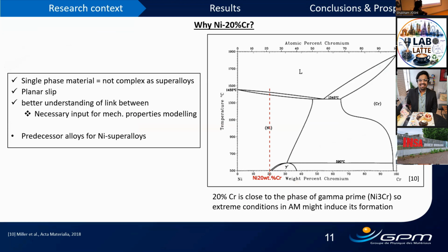If you look at the phase diagram, with 20% weight chromium, it is theoretically a monophasic alloy. It forms a predecessor for nickel superalloys, having some applications in the high temperature industry. The advantage is that it is not as complex as a superalloy, because it is monophasic, so it's straightforward. But another reason for choosing this kind of alloy is that it has planar slip, so it has a strong propensity to avoid dislocation annihilation or cross slip.